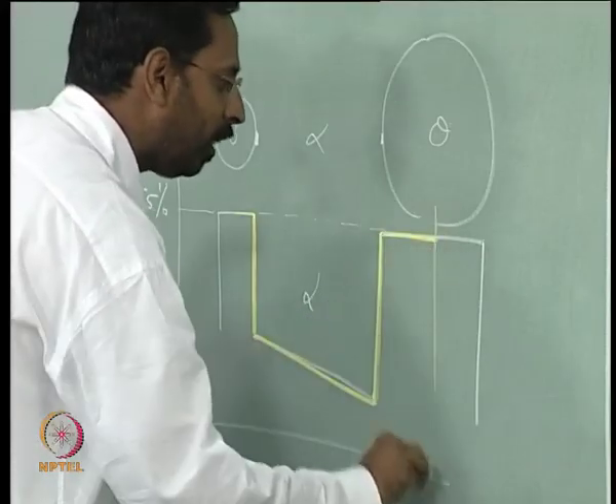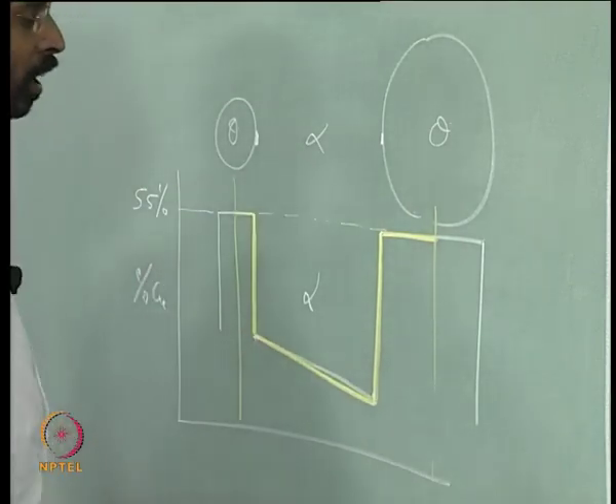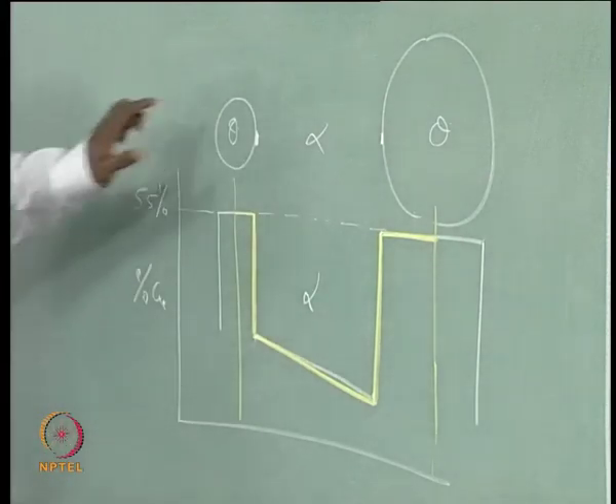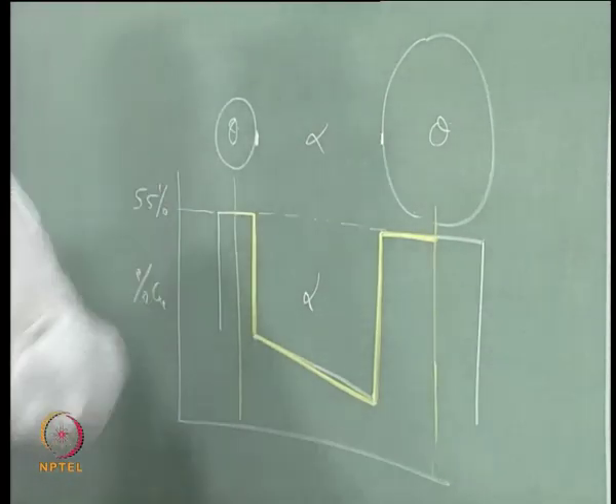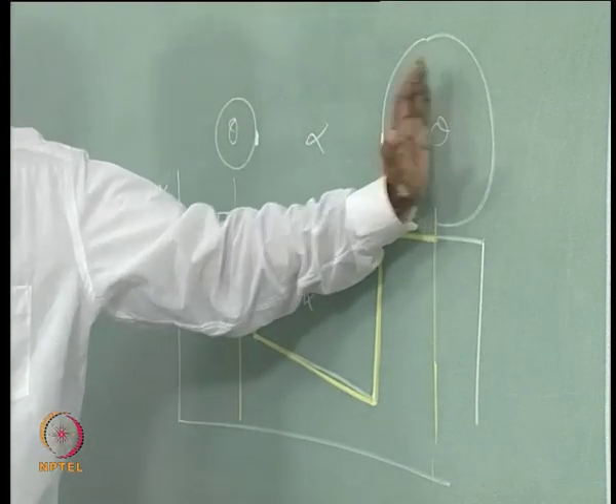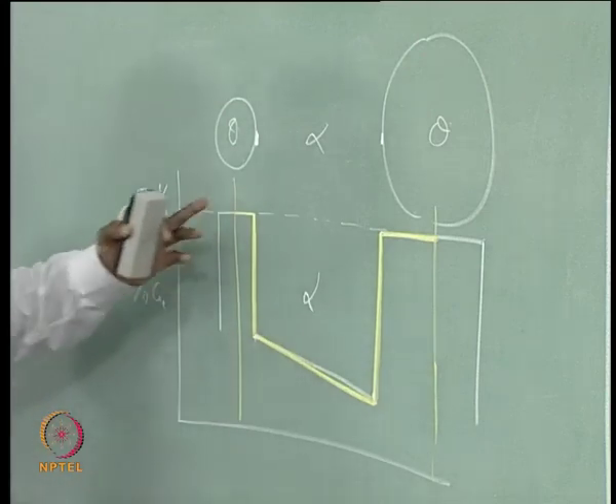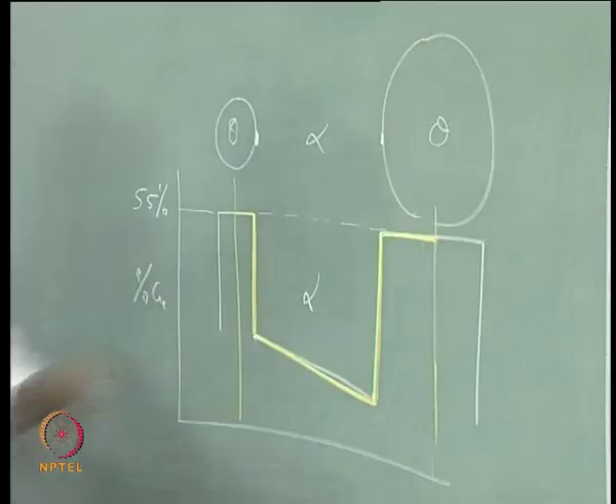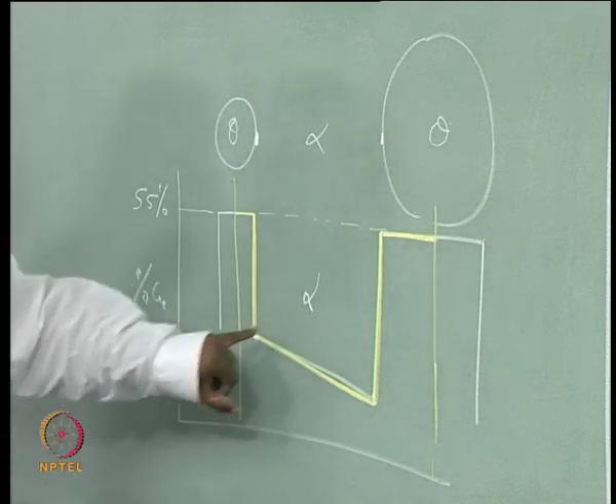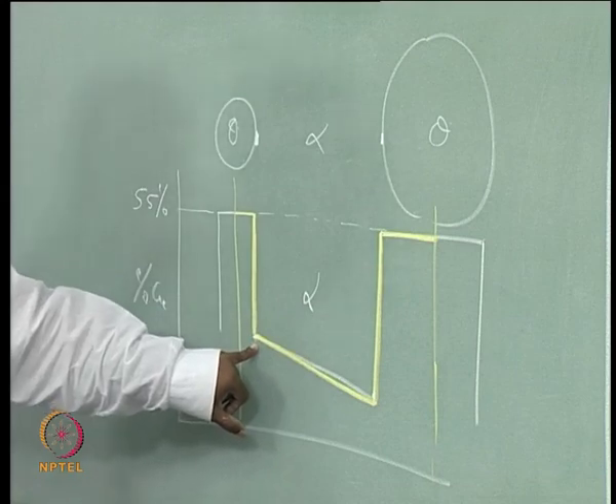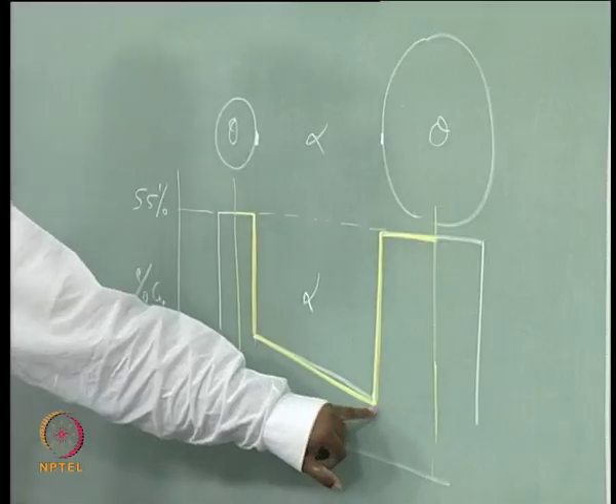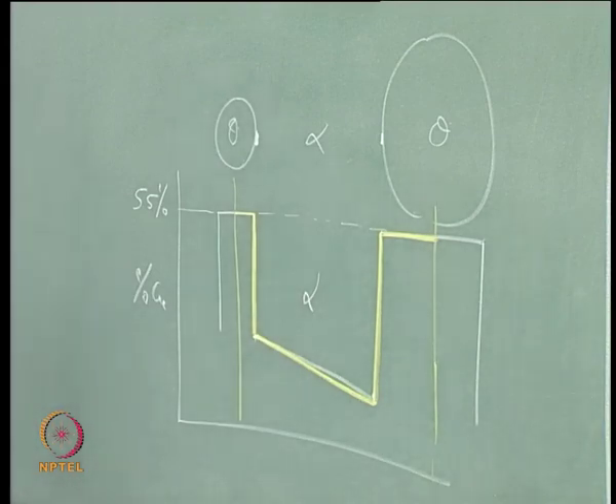If I start from the center of the particle to the center of the particle, let us not bother about the other sides, because on this side there may be another particle, on this side there may be another particle. We simply look from the center of this particle to the center of this particle. If you simply look at the composition profile, this is how you will see. Inside the alpha there is a gradient here. The alpha which is in equilibrium with the smaller particle will have a higher composition, the alpha in equilibrium with a larger particle will have a smaller composition, and once you have a gradient, you always have a